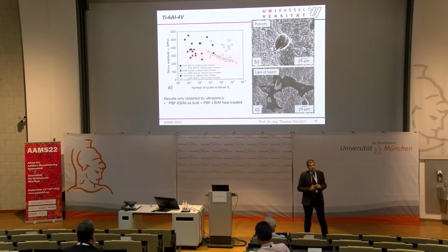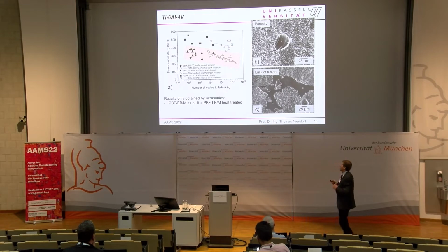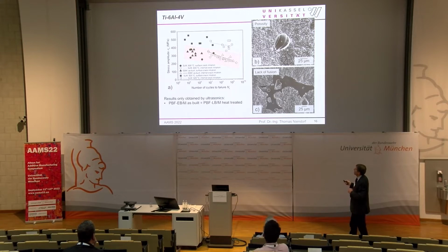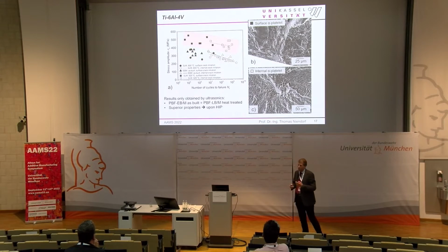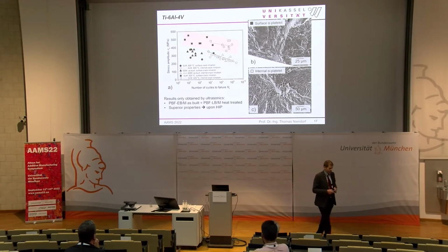And looking at the performance in the very high cycle fatigue regime, if we now consider those specimens that have not been HIPed, then they fall all into one category. So this is EBM as-built material as well as the stress relieved SLM material. So this is in principle almost on one line. This is a group of material that is then really heavily affected by those pores we see here, by the different ones, and of course most detrimental, the lack of fusion pores at that point.